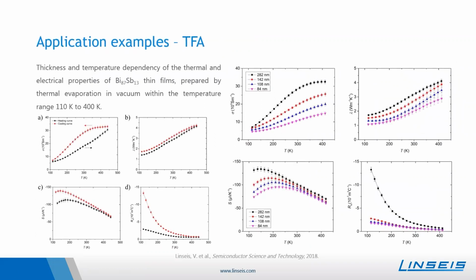So we're coming now a little bit to the end. In the next slides, I want to show just some application examples of semiconducting materials we already analyzed. Here you can see the analysis of a thin film of bismuth antimony with a thickness ranging from 84 to about 280 nanometers. This analysis was performed with the TFA, so that the full analysis was possible.